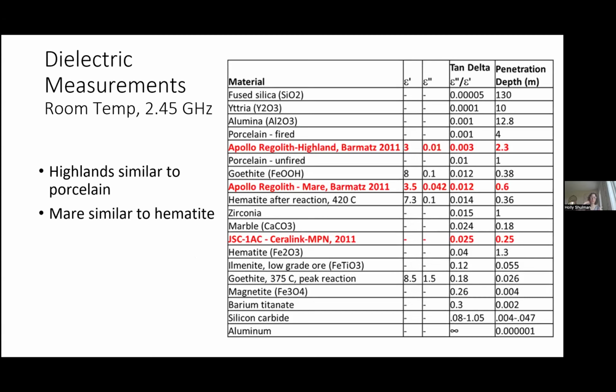This table is 2.45 gigahertz just at room temperature, but I think it's important to orient you in where the Highlands regolith is. These are actual measurements of regolith taken by Marty Barmatz, and I'm sure you didn't have too many samples, but showing that it's a pretty low tan delta, and it's fitting somewhere in there with porcelain. Whereas the Mare material, much higher dielectric loss, much higher tan delta, so smaller penetration depth. It's going to be a better heater at lower temperatures than the Highlands.